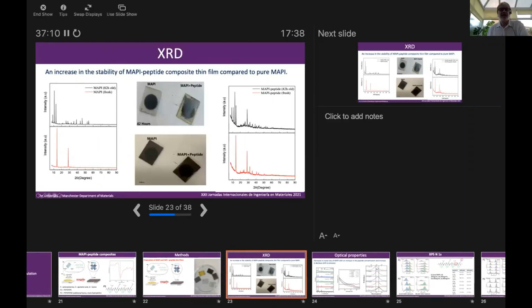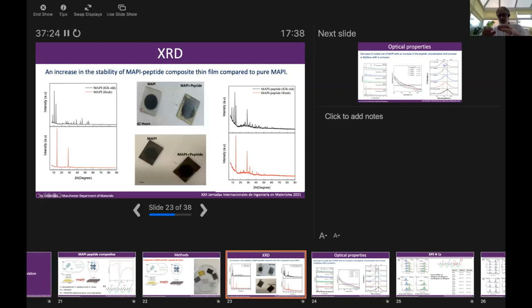And we did XRD, so this is our freshly made MAPI plus peptide and MAPI. And this is after they've been exposed to water, or water vapor, sorry, so we've got a high relative humidity. Essentially what we did, we put the samples in a desiccator, and below where the samples were sitting, we had a pool of water, a petri dish full of water. We left these for 82 hours.